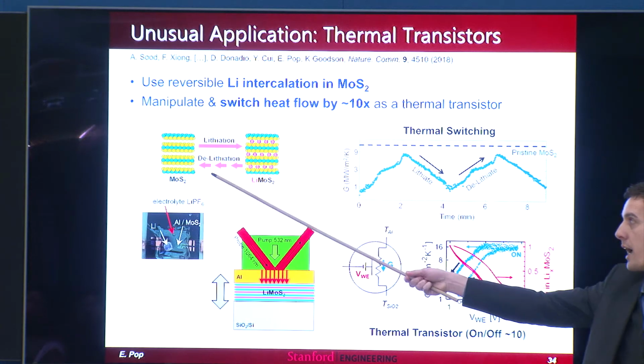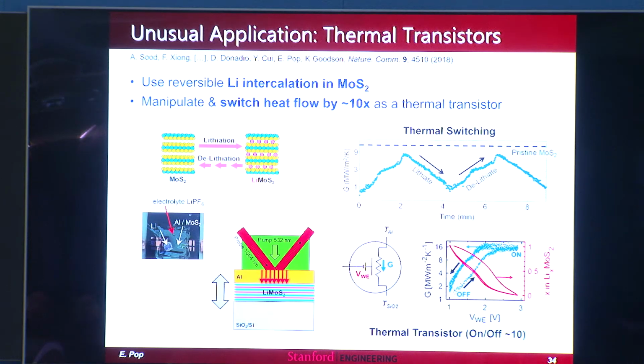Push lithium in, pull it out. Professor Yi Cui at Stanford is a battery expert, and they're very good at doing these things in real time under a thermal measurement system and so on. And so to make a long story short, here's the thermal conductance cross-plane varying as a function of lithiation and delithiation of this multi-layer stack.